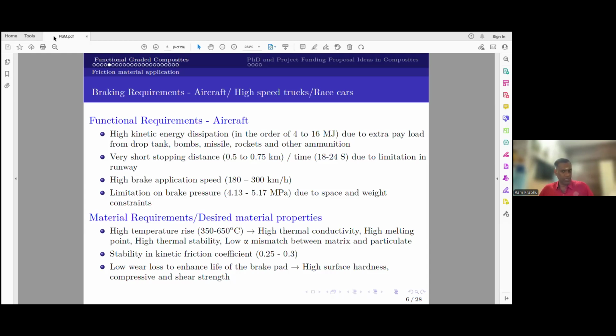I need to have thermal stability, and since it's a metal matrix composite, I have a metal and I have a reinforcement. These two should not have a high mismatch of coefficient of thermal expansion. If I have a high coefficient of thermal expansion mismatch at the interface of the particle and the matrix, there will be a high stress leading to cracking at the interface. Then your whole idea of fiber reinforcement fails.